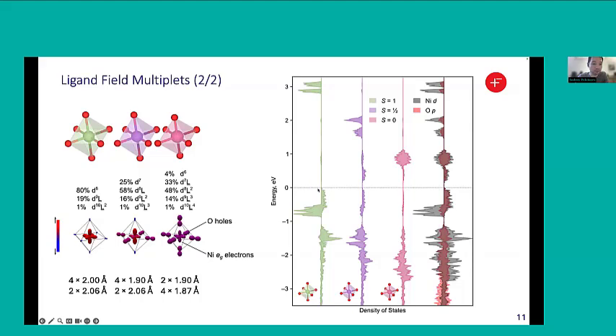So here we have these 3 different blobs, which would be electronic states that are distinct for each of the 3 different nickel species. Again, this is very atomistic, so bear with me. We will get to batteries in the end. This dotted horizontal line is the boundary between lower energy states that are full of electrons and higher energy states that are empty. We can only excite into the empty states. And we see that the 3 different nickels have rather distinct energies for their empty states. So now we can be confident that our spectroscopies can in fact distinguish these 3.